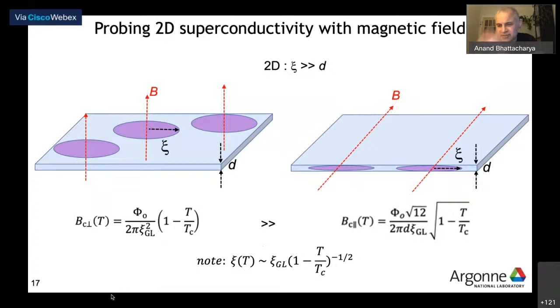Most of you perhaps know that superconductivity is killed by the formation of vortices, and when the cores of these vortices coalesce, the whole system goes normal and you recover your normal state. If you apply the magnetic field in the plane, then you don't have the two dimensions to do it in anymore, and you have to squeeze your vortex core within the thickness of your film, and that of course requires a higher magnetic field. So you can find expressions for what the critical fields should do with temperature as a result of this.